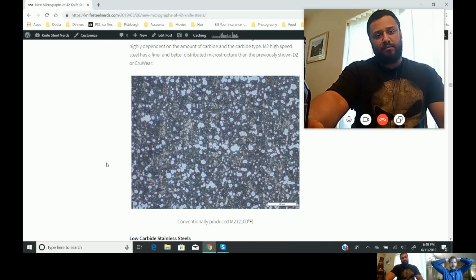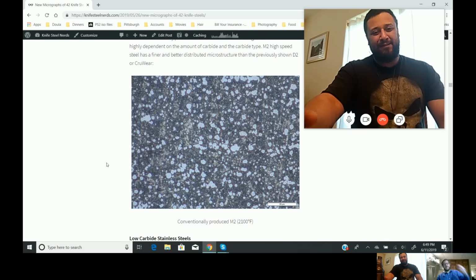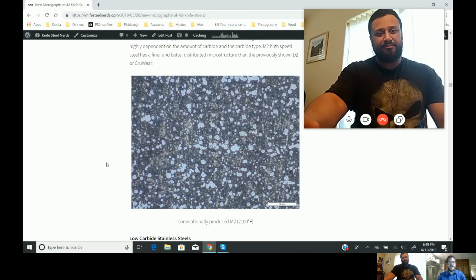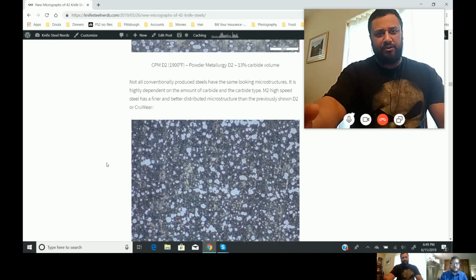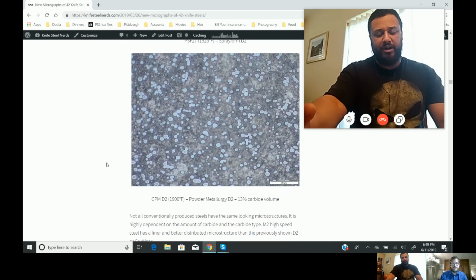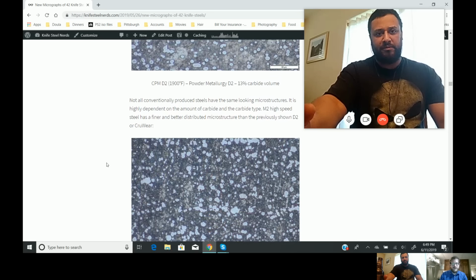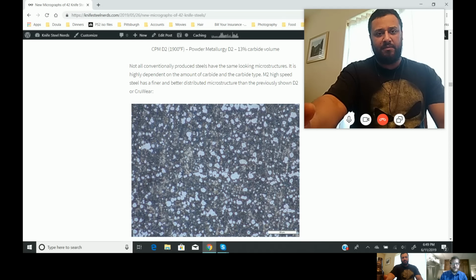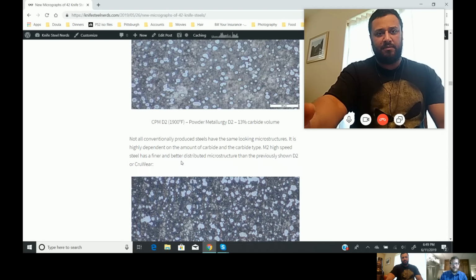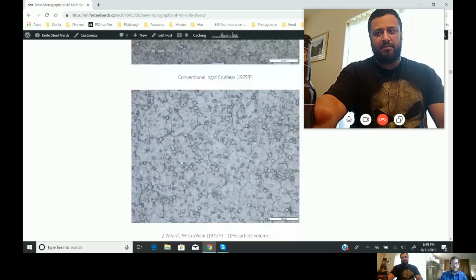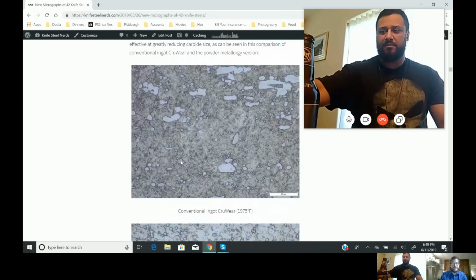It forms chromium carbides. They get pretty large. And M2 has a little bit of vanadium carbide and the rest those M6C carbides. And apparently they're able to keep them smaller during the solidification and forging process. I mean, go back up to CPM-D2. Is CPM-D2 even that much finer than the M2? Yeah, not really. I mean, there are some larger carbides in the M2, but overall it looks pretty good. It looks finer than the conventional CruWear too.